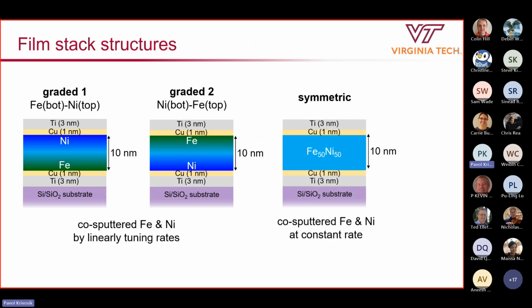Now, and also for good measure, we also had a control sample in which we had no intentional compositional gradient. So here, the composition is supposed to be uniform throughout the film thickness. Right. So at this point, some of you may be wondering why we have this seed layer and also a capping layer consisting of titanium and copper. So very quickly, titanium is a kind of a nice adhesion layer. So it allows for the subsequent film layers to stick better to the substrate and go in a smooth fashion. And we also knew from our previous experience that having just even a very thin layer of copper tends to reduce the amount of effective damping, or more technically, the ferromagnetic resonance line width in the ferromagnet.